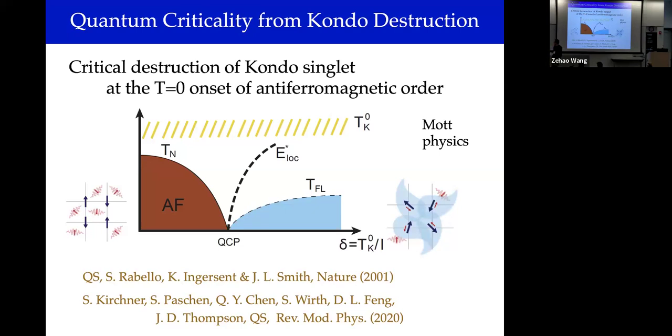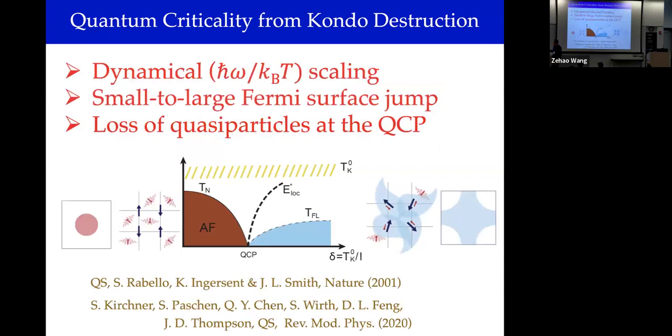And that kind of quantum critical point goes beyond the Landau description in the sense that fluctuations of the order parameter are not the only critical degrees of freedom. So it turns out that the criticality associated with the amplitude of this Kondo singlet, which again goes beyond the Landau because it doesn't involve spontaneous breaking of global symmetry, leads to a number of observable consequences.